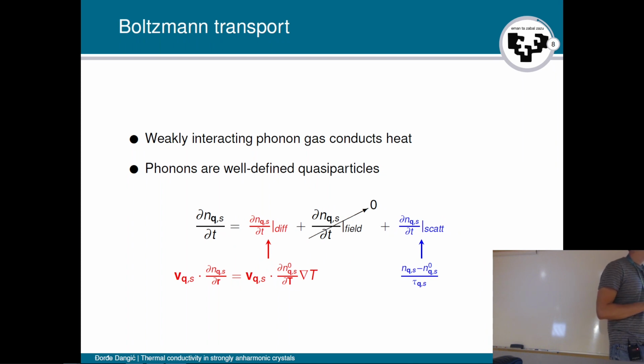So the phonon population of this state changes due to the scattering between phonons, but what we do here is linearize the Boltzmann transport equation. So say that if we have some excited population of the phonon, n_qs, it will relax to the equilibrium population, n_qs naught, in some characteristic time, tau_qs, which is characteristic for each phonon mode, and this characteristic time we are going to call the phonon lifetime, or the relaxation time of the phonon population.